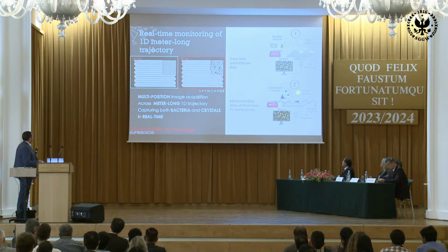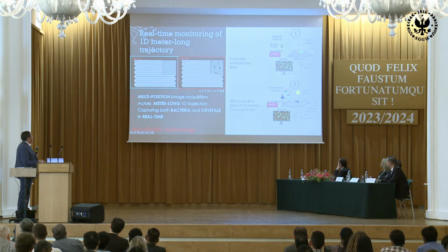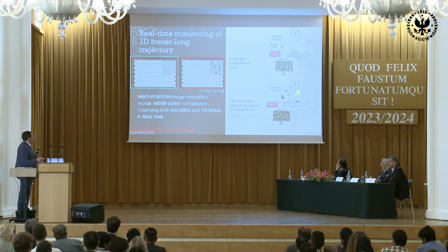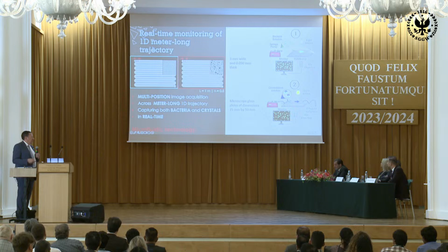I will show you results of two cases that have the same porosity but different distributions of grains. The system is based on the fact that we first inject with a syringe pump our bacteria solution from one side, then we inject from the other side our cementation solution, mainly urea, and we use cameras to follow what is happening in the PDMS chip. This is the type of result that we can get. I'm showing the results almost in the middle of our 1 meter long chip.